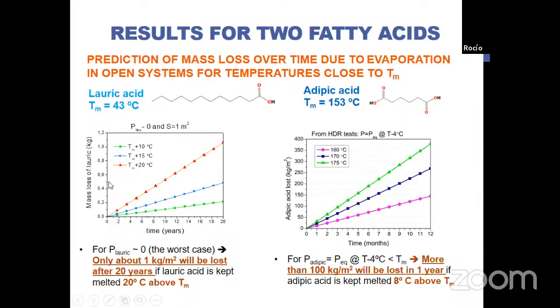Here you have the results for the lauric acid and also for the adipic acid. Lauric acid has a melting temperature of 43 degrees, for low temperature applications. However, adipic acid, at 153-154 degrees, is quite an interesting material for mid temperature applications. This is why it is also an interesting PCM to study. So what we see in these two graphs is, let's say we have lauric acid in an environment in which its pressure is almost zero, so we are removing all the material that is evaporating.